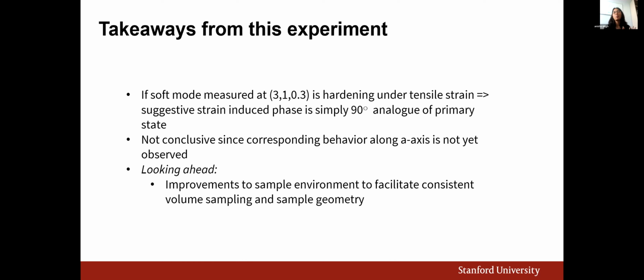Now, this is not quite the complete picture, since we have not conclusively observed the corresponding behavior along the A-axis, right? So we would want to see softening of that same phonon mode along the A-axis as the CDW order is reoriented along that direction. Like I mentioned very briefly at the beginning of this talk, though, performing measurements along both the C and A axis simultaneously in the same sample is challenging, because of the geometry of the Razorbill cell, we can't access both orthogonal directions in a single sample because of how the crystal is mounted. There are some screw plates that again block the beam.